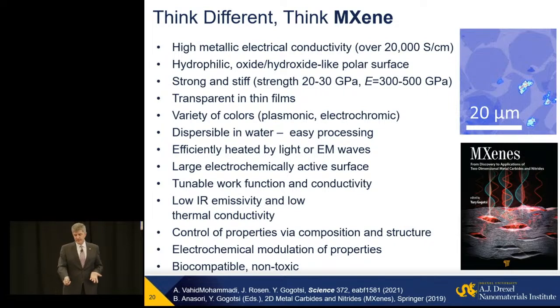With MXene, we can take these flakes, assemble them in MXene paper, like a film, spray on the surface, and we get 20,000 to 25,000 Siemens per centimeter. So about 10 times better conductivity, higher conductivity.